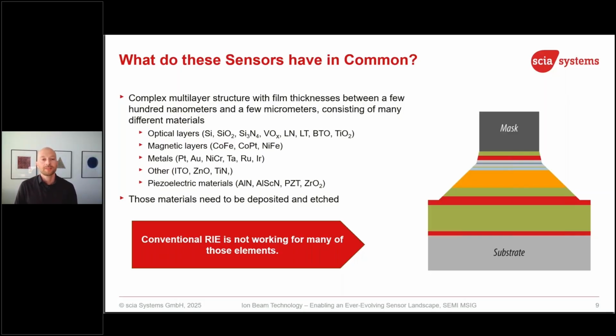And the challenge now is that RIE is not working on many of those materials. Of course, for silicon, silicon nitride, silicon dioxide, there are RIE etchers available, no problem to structure those. But for a lot of other materials, maybe platinum, PZT, lithium niobate, you cannot etch them with an RIE process. So ion beam etching is a good way to do it. On the right side, just an example of how such sensors could look like: many different materials in a stack, a mask on top, which could be photoresist or a hard mask. So our customers use both.